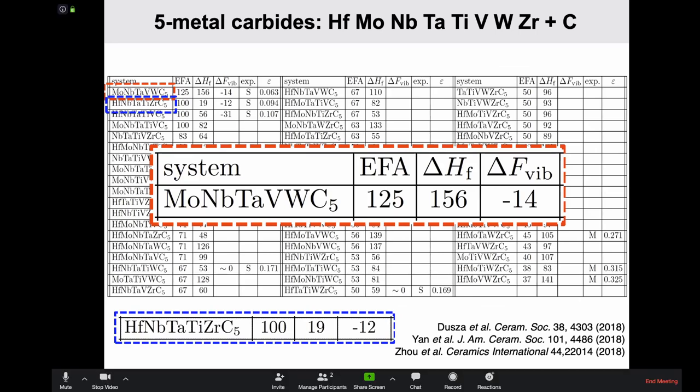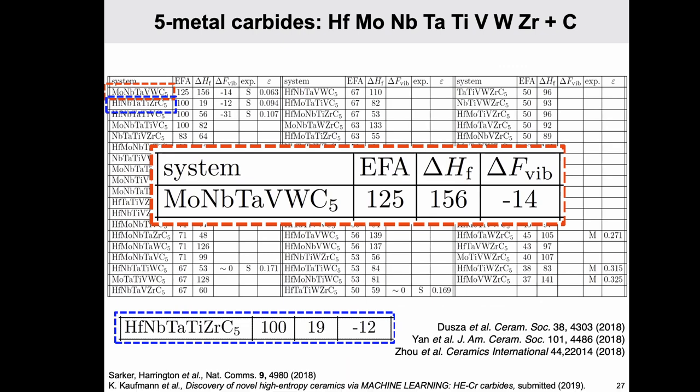Yes, but let me tell you, in our experience, the high temperature disorder phase is almost always very simple. So prepare to have a rock salt or a B1 or B2, right, or a very simple crystal structure. You don't really need to try them many. It's more a configuration entropy, then the way you access the states, then the configuration of the underlying lattice.